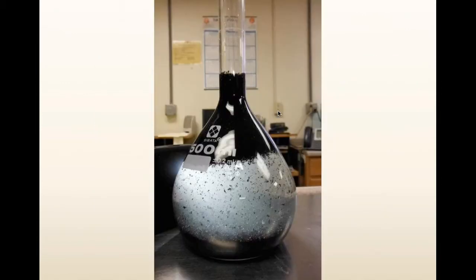This picture I just took is interesting. This was running when I was first experimenting, looking at the gravity of rubber itself. One of the reasons is that the asphalt itself can migrate, and when the material is densified, the liquid asphalt is the lighter gravity. Stone has a gravity of about 3. Asphalt has a gravity of about 1. So the asphalt's naturally going to float to the top. The neat thing is when you put this particle of rubber in, the rubber's gravity is also 1. So it kind of says, shoulder to shoulder, to the asphalt, hey man, stay down here.